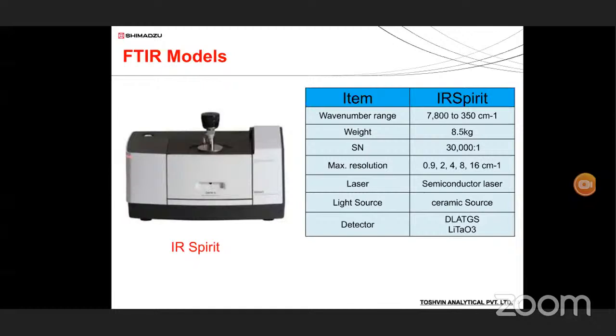The IR Spirit covers the mid-IR range, from 350 to 7800 centimeter inverse. Ideally we run the spectrum in the mid-IR region, from 400 to 4000 centimeter inverse. When we are using FTIR with the ATR, we recommend using the range from 650 to 4000 centimeter inverse. And the weight of the IR Spirit is very light, around 8 to 8.5 kg.